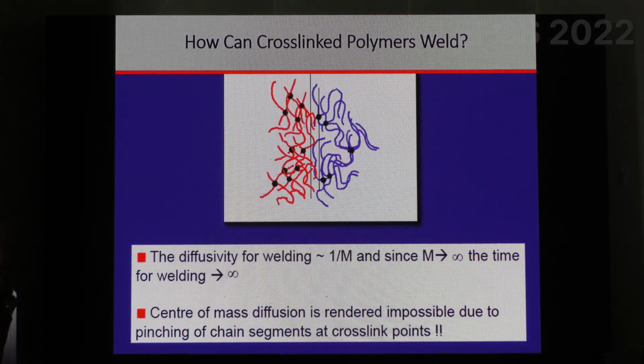Now this is very interesting because, in milk pouches, if you heat a milk pouch, you will seal it, right? And that sealing happens because the polymer chains actually go through the welding, and they diffuse and they start entangling with each other. And that's how sealing happens in plastic polymers. And that happens because the polymers can actually migrate. There is a center of mass diffusion of the polymer from one side to other.